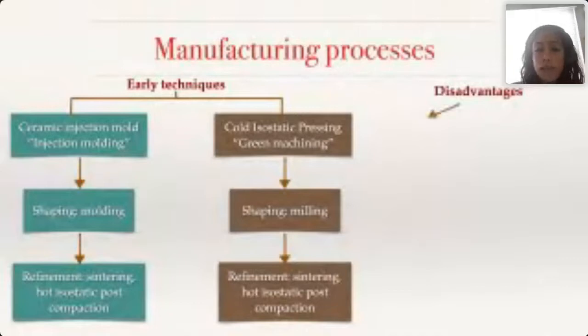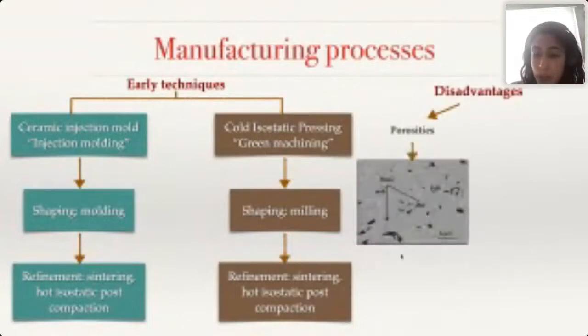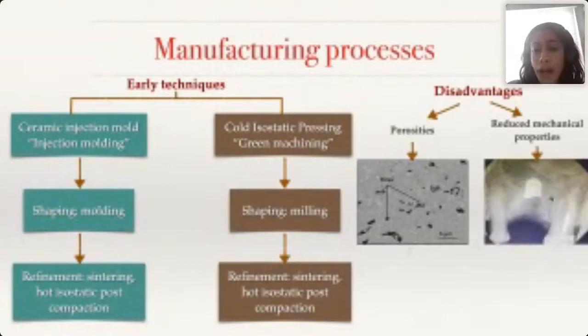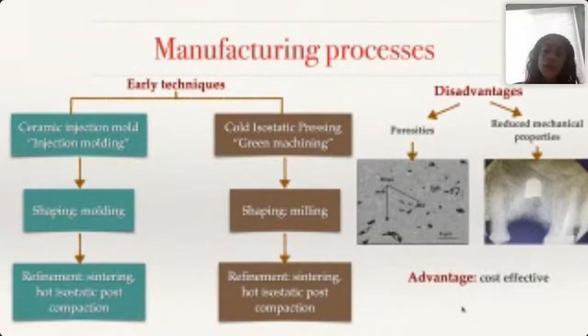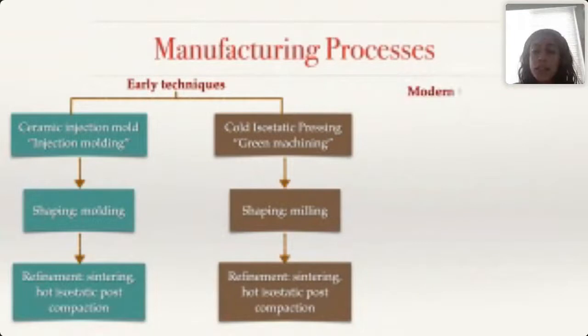These early techniques do have some disadvantages because there is a binder involved with the initial material. When the binder evaporates, we can end up with porosities, and these porosities can reduce the mechanical properties of the material. We want to avoid this by reducing the chances of getting porosities. The advantage of this technique is it's cost effective and cheaper - a lot of implants can be produced this way, but not necessarily the safest way.